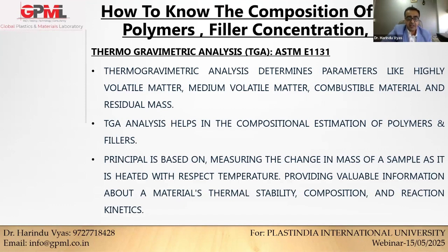The principle I have told already is that it measures mass loss versus temperature. The last result obtained from TGA is the residual mass, which is the filler content, that we can also get with the normal muffle furnace process. If we just want to find filler content, we can use the muffle furnace process rather than doing this expensive test. But using these three in combination, TGA, DSC and FTIR, we can estimate the very important and rather challenging thing, which is the composition of the material used.